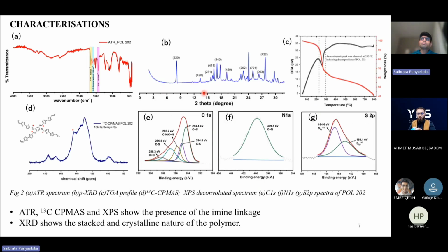So after the synthesis, of course, what any organic chemist would do is a certain amount of characterization to be sure the material is what you expect. And this is a basic characterization of the whole thing. You do an XRD, an ATR-FTIR, and then TGA to understand the weight loss and how it is behaving, and of course an NMR, the solid-state NMR. These kinds of materials are highly insoluble in normal solvents, and that is why we go for SSNMR, the solid-state NMR, rather than a normal NMR.